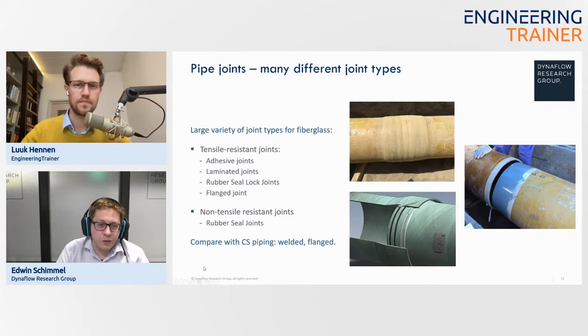And in total, you test 20 samples at different durations, according to the ASTM code, and then you also perform other tests at 1,000 hours, again described by another ASTM code. So you have a lot of ASTM codes that describe the specifics of the individual tests, but it's all brought together by the ISO 14692 design standard. You also have other design standards. Some also use the same philosophy of long-term testing. There are also codes that specify only a short-term test, a burst test, to be performed, but then a really large safety factor is used. That's also possible.